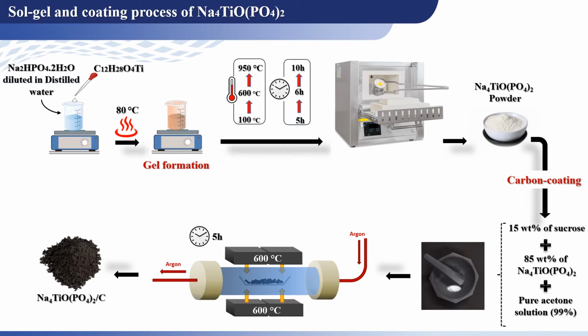The synthesis of our sodium titanium phosphate was done by the sol-gel route by mixing a stoichiometric amount of disodium hydrogen phosphate dihydrate dissolved in distilled water and titanium isopropoxide. After the addition of titanium isopropoxide, we obtained a gel which was dried at 100 degrees for 5 hours and then annealed under air at 600 to 950 degrees for 6 and 10 hours, and by the end we have obtained a white powder.